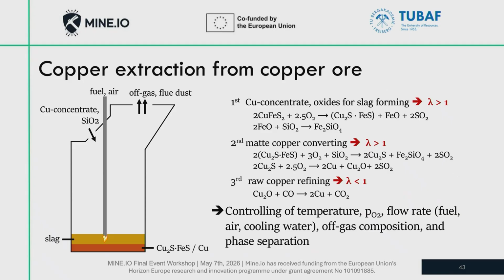Coming from the froth flotation process, we have copper concentrates going into our copper production process for raw copper production. The copper concentrates need to be handled in oxidative environments to produce matte, and after matte converting, we have a reduction process to produce raw copper. This can be done, for example, in one of those furnaces, and very important here are the slag composition and of course the control of the temperature, the pO2 of the off-gas system or of the atmosphere, the flow rates of fuel, air, cooling water, the off-gas composition, and also phase separation. Those are all very important data points to drive those processes safely and with high efficiency.